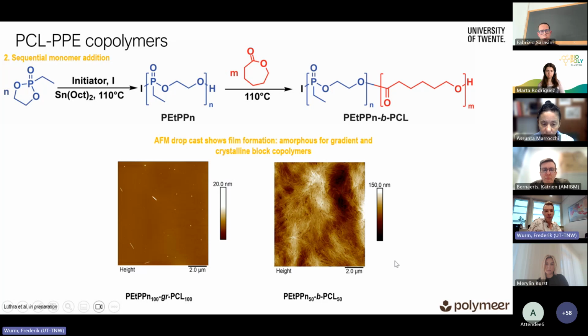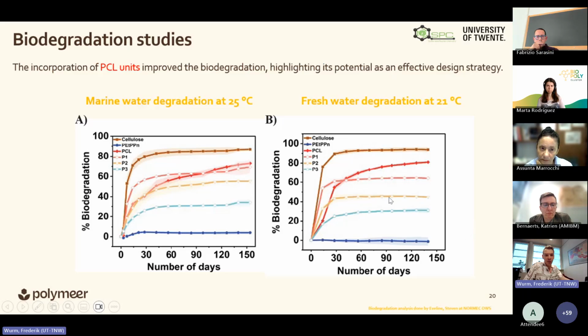And what is interesting is when you compare a block and a gradient copolymer, and this is just a drop cast of the solution. The right side is a block copolymer, so we get nice crystalline structures, because polycaprolactone can crystallize, while in the gradient structure, we keep the polymers fully amorphous. And of course, this also influences in the end the biodegradation kinetics, where the material ends up. And this is what our project partner in Belgium studied in the project.